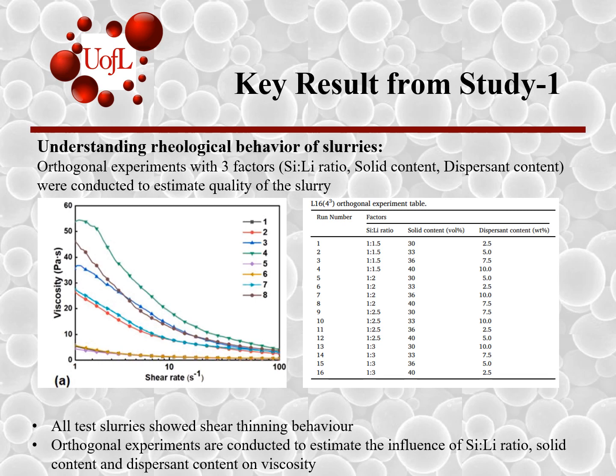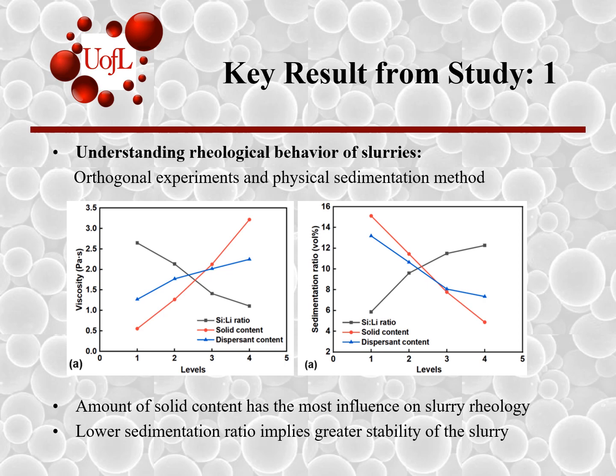The variables for evaluating viscosity are the mass ratio of the precursor sources, silicon to lithium, the solid content, and the dispersant content. On the right side, the table specifies the set of experiments with different combos of these three variables. On the left, we see the shear rate dependent viscosity of the samples. A shear thinning behavior is observed where the viscosity drastically decreases with an increase in shear rate. On the left, we have the result of orthogonal experiments which shows that viscosity decreases with an increase in lithium content. It increases with the increase in solid content and the dispersant content too.